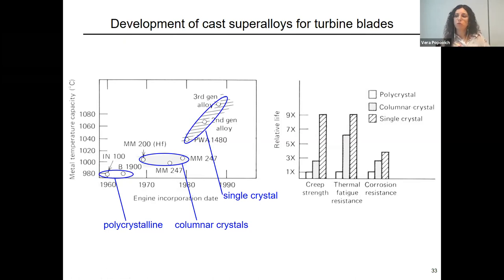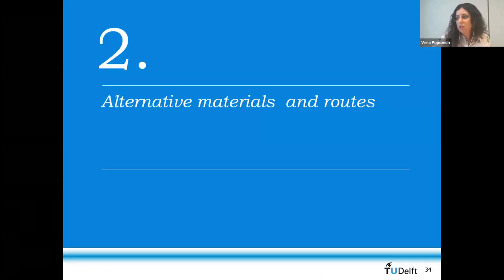Besides the chemistry, for sure the grain structure and the processing play a very crucial role, because you can imagine that in the 40s, 50s, or 60s, a lot of effort was just on polycrystals and how the grains can be strengthened and so on. And there was not even close to how much they managed to reach when we changed the grain structure. So it's 3 times to 9 times. With this, I finish the introduction into what was before.